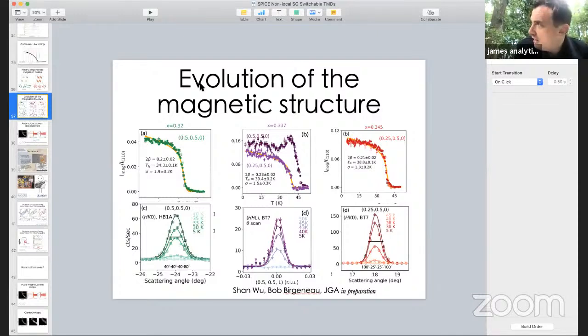And so far, structural disorder is an interesting thing to know as well. But as far as we can tell, we've done a lot of TEM work, and even though sometimes there seems to be disorder in the stacking of the layers, the actual layers themselves seem to be very well crystallographically ordered. But anyway, your question's really about the magnetic structure, and our strategy is really just to try and get some microscopic measurements, and I feel like that's what we've done.